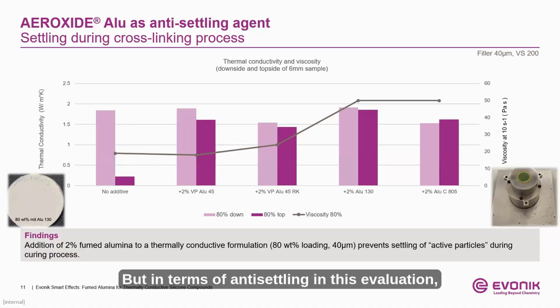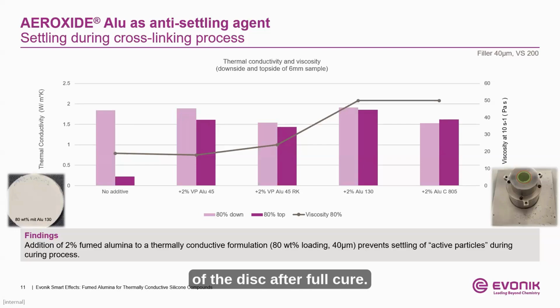But in terms of anti-settling in this evaluation, we no longer look at the settling of the material over the storage life of the uncured silicone, but we now look at the settling of the material post-application and during the curing process as a function of thermal conductivity. Again, to do so, we cured the 6 millimeter disc and using the C-Therm thermal conductivity measuring unit pictured here to the right, measured the thermal conductivity of both sides of the disc after full cure.